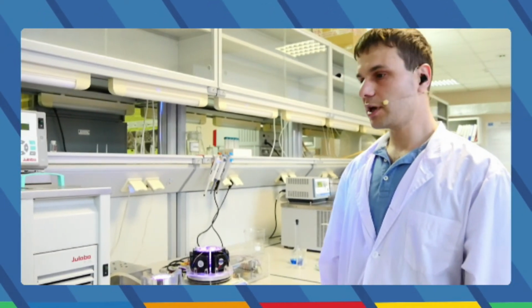In the South Ural State University Nanotechnology Center, we developed a new way of preparation of this material. As you know, titanium dioxide has some drawbacks in its application. Its most active allotrope modification, anatase, is not stable, first of all, and another drawback is irregular shape. Here we developed a special way of preparation, which we call the peroxide route, which allows us to prepare spherical shape particles with desired size, which are desired to use in flow processes, and these particles are very useful to handle.